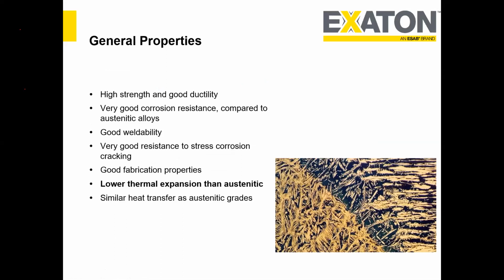So when you talk about the general properties of duplex, why are we looking for a duplex structure? We know that austenitic stainless steel has a few good properties, like very good impact properties. It can be used even in cryogenic applications down to minus 196 degrees centigrade. But on the other hand, it does not have good pitting resistance or corrosion properties. The ferritic stainless steel has good strength and better corrosion properties, but it is inferior in terms of toughness. So if we combine these two structures into one, we can optimize both the mechanical properties as well as the corrosion properties. That's what we are trying to achieve with this duplex structure.